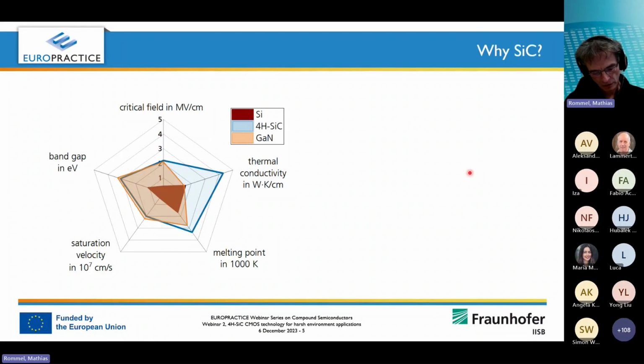Still, I would like to show some comparison between 4H silicon carbide here in light blue, silicon and gallium nitride, which you already heard of in the first talk given by Ahmed. So especially for power devices, we have several important parameters, like the critical electrical field the material can withstand, the band gap, the saturation velocity of the carriers, the melting point, which is partly important, but also the thermal conductivity, which is very high for silicon carbide, which makes it ideal also for high power systems.